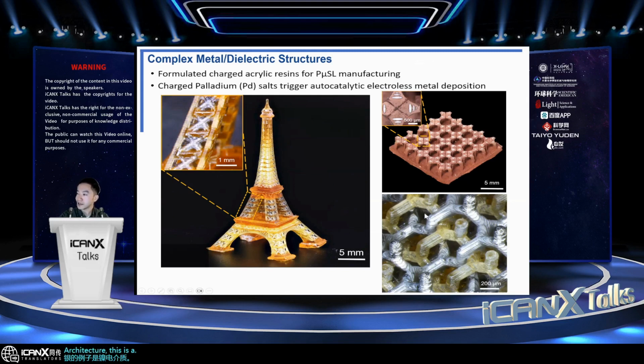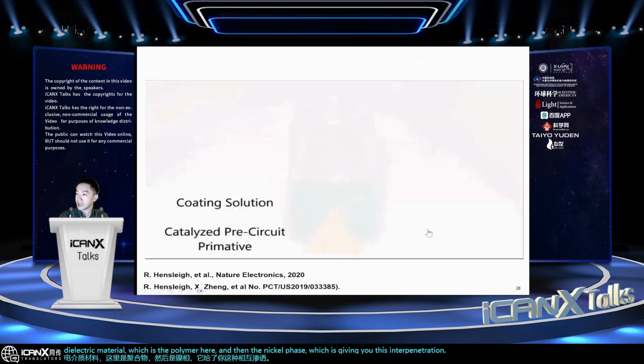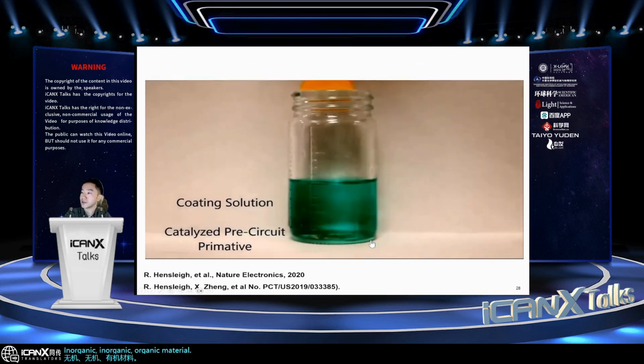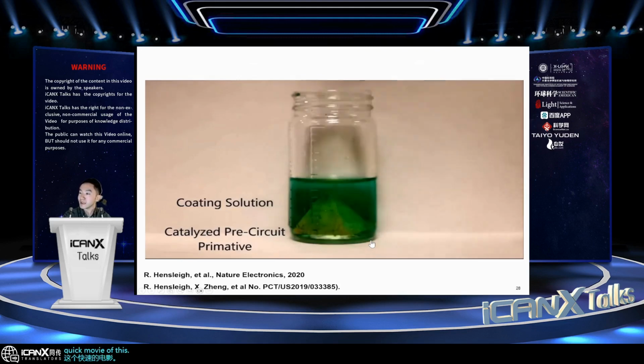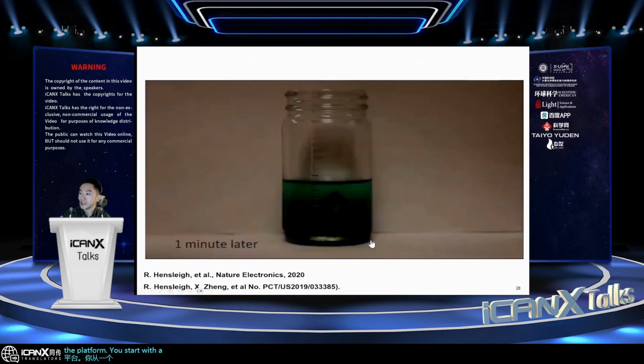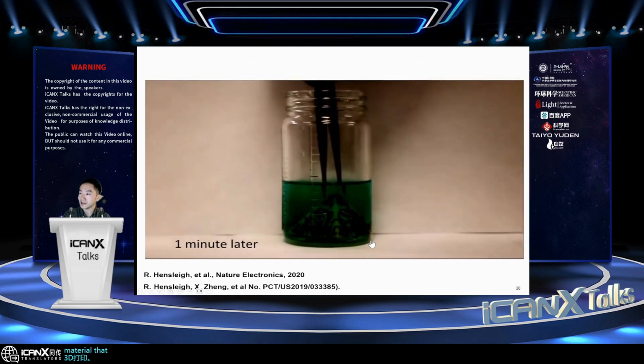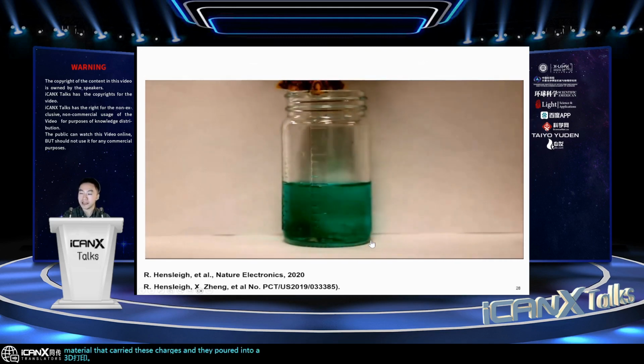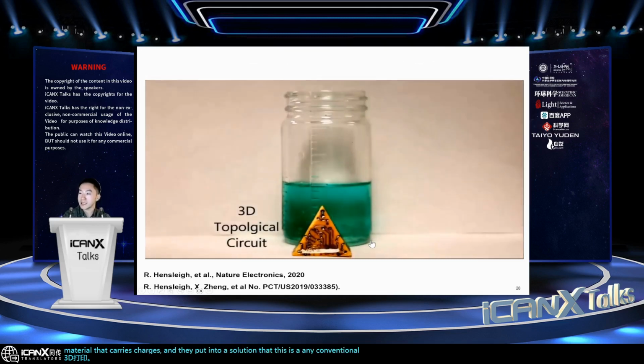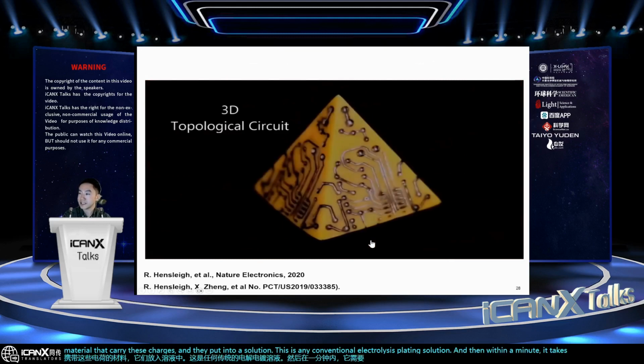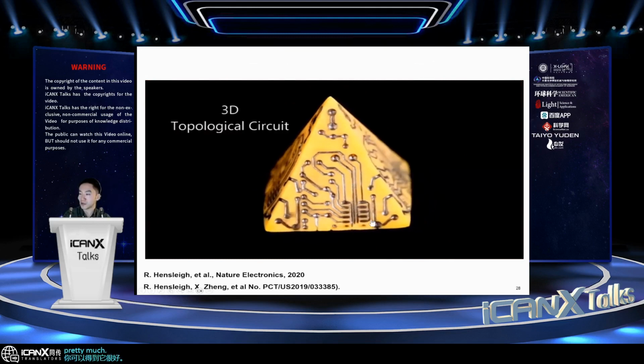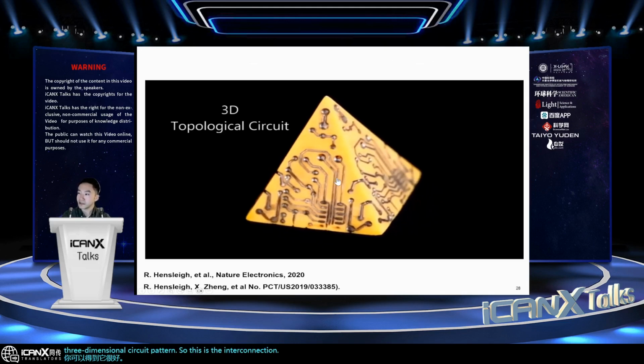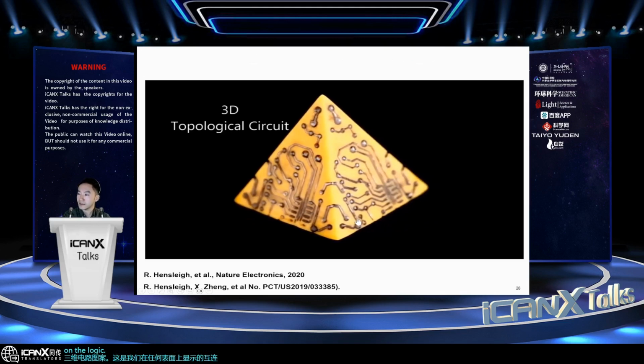This is an interconnected dielectric material, which is the polymer here, and then the nickel phase, which gives you this interpenetrated inorganic and organic material combination. And here I show a quick movie of the platform. You start with a 3D printed material that carries these charges, and then you put it into a solution. So this is any conventional electroless plating solution. And then within a minute, you take it out, and you can get a nice three-dimensional circuit pattern. So this is the interconnect we show at any surface with any topological complexity.